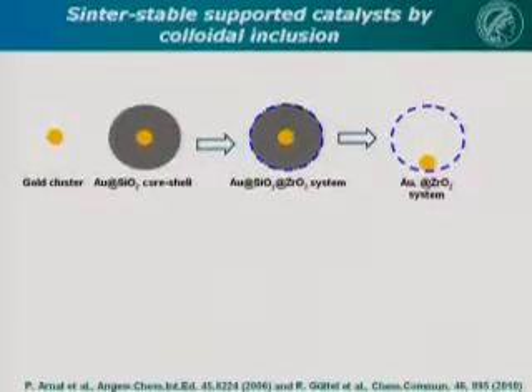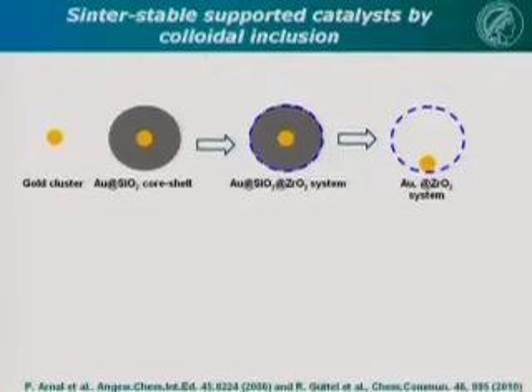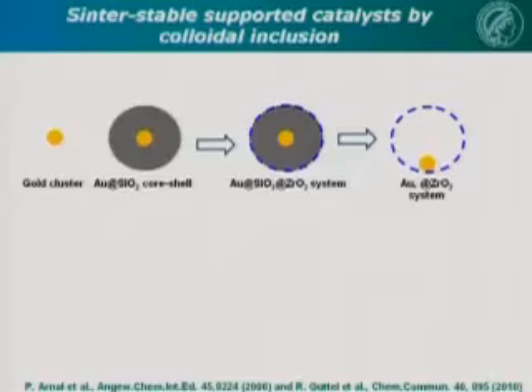The way to do it is you start with a gold cluster, in this case 15 nanometer in size. They work best, one has to say. We would like smaller gold particles, but the 15 nanometer ones are the best, actually. Then you take the well-known Stöber process to make monodisperse silica particles, where we can adjust the size between, let's say, 50 and 200, 250 nanometers. Then we coat the silica by a porous zirconia shell, and we use zirconia because it has very high thermal stability. And then we leach the silica with sodium hydroxide, and we have a gold particle in a porous zirconia shell.